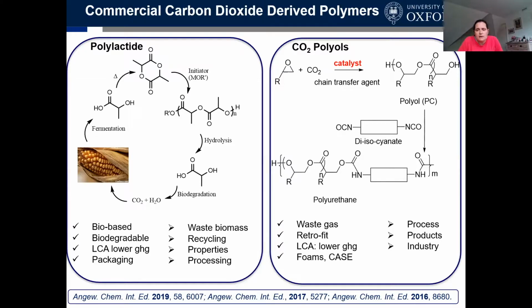And what we mean here is where we take carbon dioxide and epoxide and a catalyst, and we make a polycarbonate. So the carbon dioxide ended up in the backbone of that polymer, and so did the epoxide after it got ring opened. And that polycarbonate is low molecular weight typically and has hydroxyl end groups, and that's why it's called a polyol, because it's got hydroxyl end groups, and those then can react on with a diisocyanate and give you a polyurethane in one manifestation of a common use of the polyols. There are other uses too.